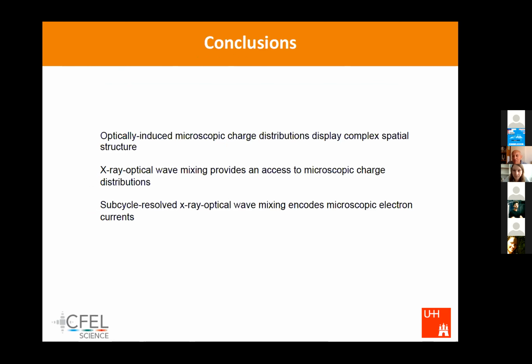May I ask a simple question, Daria? Your work is more theoretical. How do you compare your results with experimental results? Yes, so far I have shown you theoretical results, but we have experimental collaborators on the time unresolved case. That has been measured relatively recently at SACLA. The preliminary results say that they do observe these side peaks to the main Bragg peaks. So yes, it's possible experimentally.